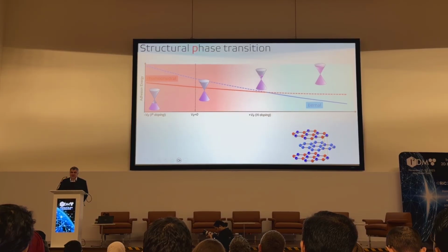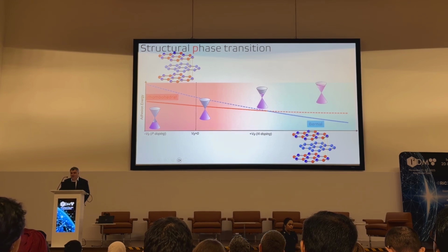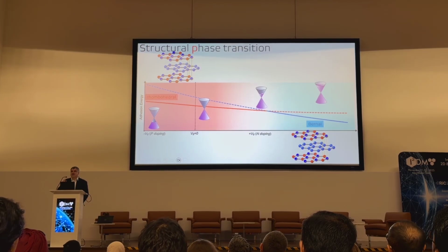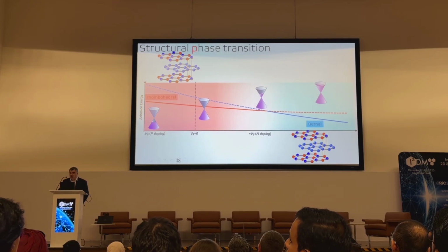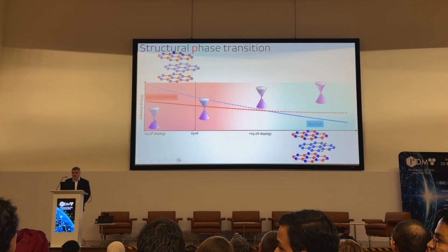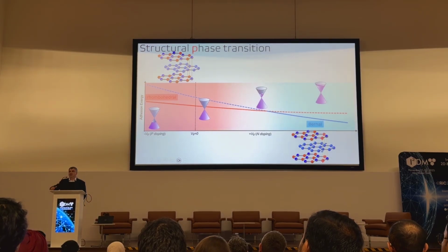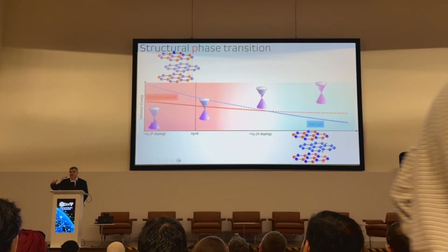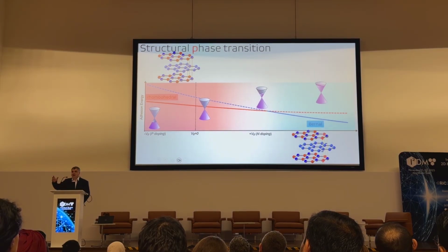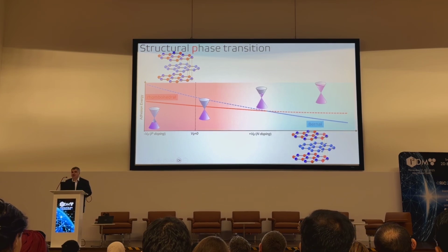And it's quite easy to see why it is happening. Like here on the right hand side, right bottom diagram. The red atoms are the boron atoms, and boron atoms are slightly positively doped due to the covalent bonding to nitrogen, and so we have a little bit of positive charge sitting on them. But now, imagine if I charge graphene with a negative charge, they interact in an attractive manner.